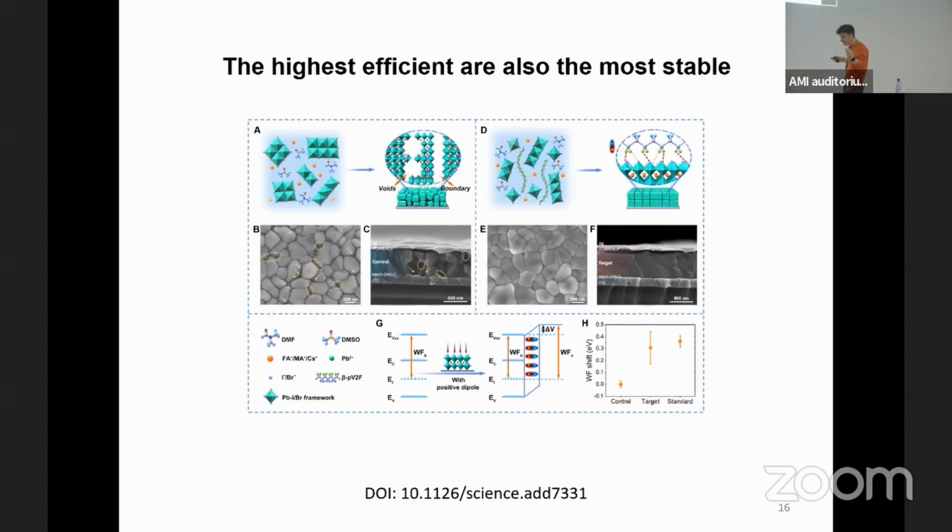But what I believe is really important here is that, considering the amount of polymer that we add into the system, we managed to coat the crystallites within the perovskite film with a thin shell made of polymer, which is soft. And so when we age the device, we induce stress. I do believe that the mechanical stress that we create in the system causes degradation, and by using this polymer we prevent this mechanical stress. If you read the paper, there's nothing mentioned about mechanical stress, but that's what I understand about the system.